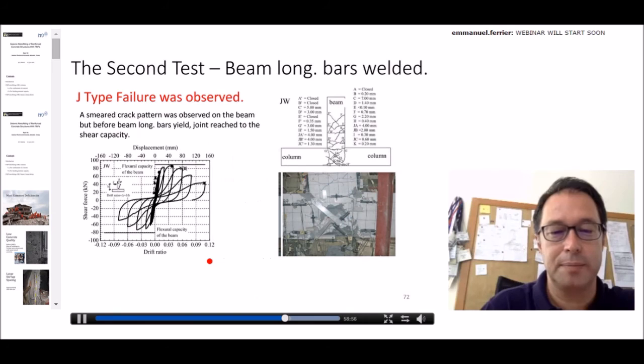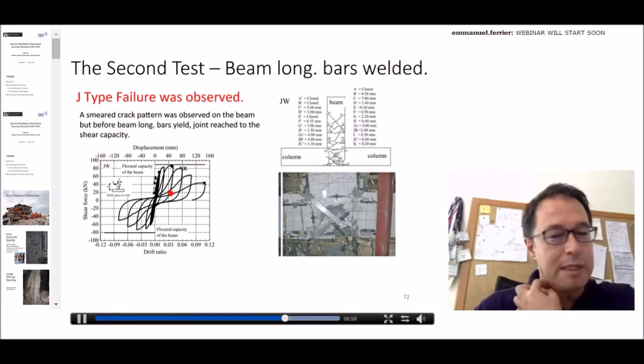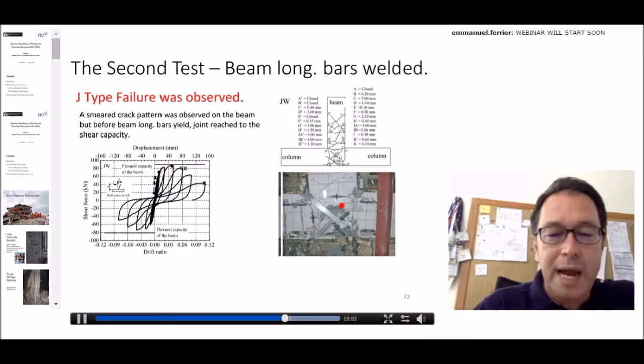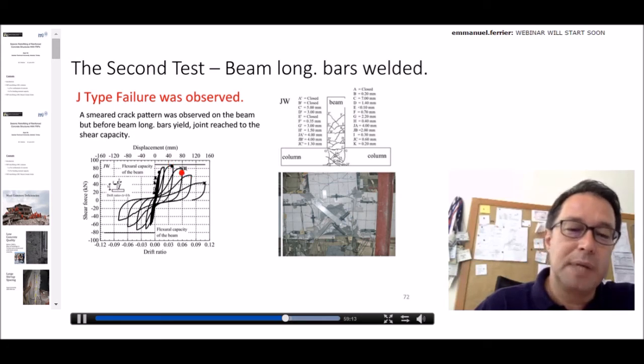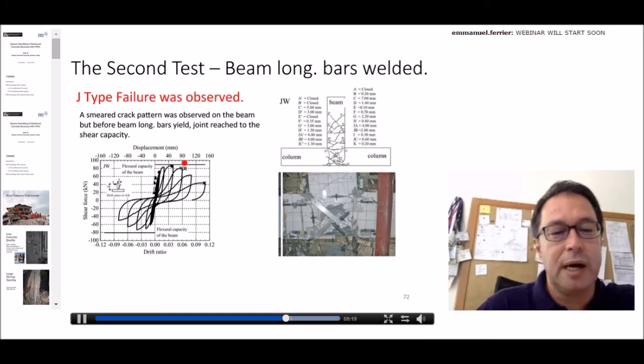And then the behavior was like that. We could reach higher strengths, and we didn't have slip here, but then we had a joint failure in shear. As you see here, the joint damages were more severe, and the behavior is, I could say, more brittle with respect to the slip case. In case of slip, we had larger displacement capacity without losing the strength.